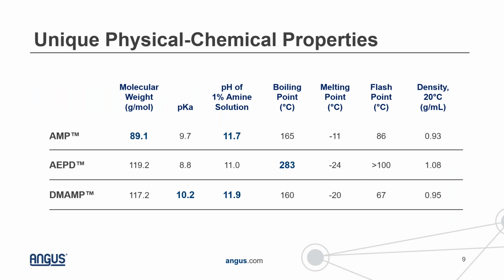And the reason why that is, some of the properties of these materials are different from one another, right? So if you look at this table, this is showing some of the different physical and chemical properties of these materials that arise from the chemical composition of these molecules. So a couple things I can draw your attention to is, for one, you have molecular weight. So AMP, the molecular weight of that material, is the lowest out of these three. It also has a fairly strong pKa. So the pKa of 9.7, that reflects how strong a base that material is. And so in the case of AMP, because of that low molecular weight and relatively high pKa, it's a very efficient neutralizer. So you don't need to use that much of it in order to have a strong effect on the